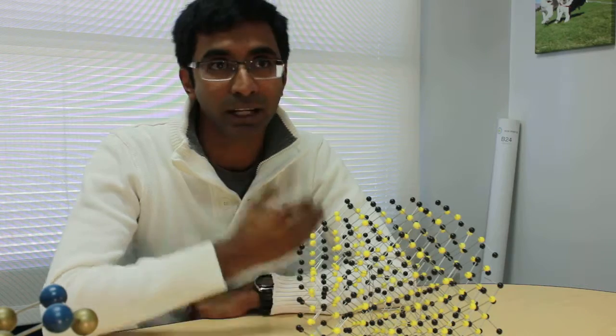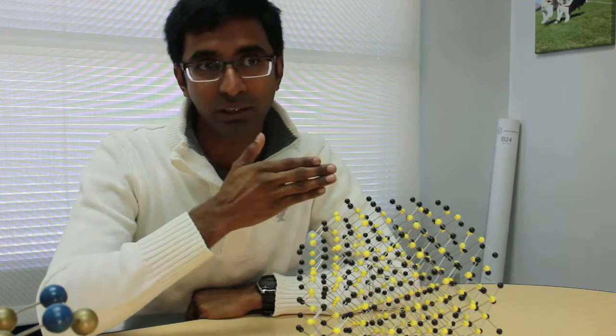So you must keep in mind that the cooler something is, the further it is in the infrared. So the human body radiates photons as well, but it does so at 8-9 microns or even longer. A hot kettle might radiate somewhere at 3 microns or 4 microns. A propane flame is very hot if it's direct, but an indirectly heated object, some other object that's heated by a propane flame, could perhaps be at 2.4 microns. And if you get to something as hot as the sun, then it's 500 nanometers and shorter. So you can see that the hotter something gets, the closer it gets to ultraviolet, and the cooler something is, the closer it is to infrared.